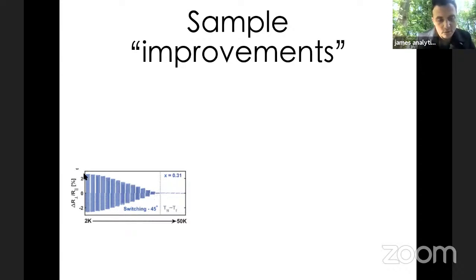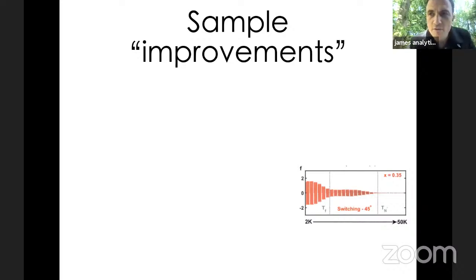So because the signal grows like an order parameter and it saturates at lowest temperatures. So that was fine. Now look at the over-intercalated samples. Sure, the pulse trains turn on at around the Néel transition, just as you expect, but then it kind of levels off, and then at some intermediate temperature that I've called TF here, it starts to turn on again. Now I want to emphasize, there's no phase transition that we know of at TF. There's no other kind of magnetic order that turns on there.